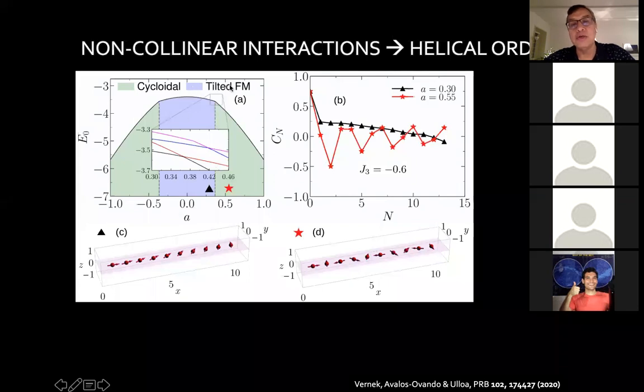then we are in what is called a tilted ferromagnetic configuration, which is indicated here. You can see that there is a slight tilt of the spins as I move along the chain, but they're locally ferromagnetically coupled, right? They're parallel to each other for the most part with this low tilt as I go along. On the other hand, if this Dzyaloshinskii-Moriya strength is larger, now I'm in this green region, on either side, positive or negative. So I'm in this star here, and the cartoon that appears is more like this.